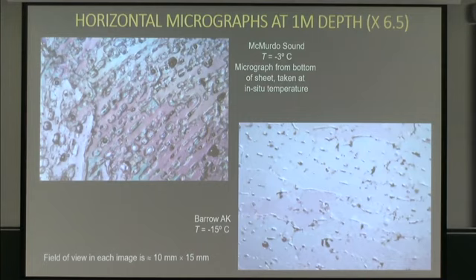So our brine inclusions don't just sit there. It's very dynamic. All these little odd-shaped things you see here are actually tubes and little pockets of brine, but very close, -3 degrees, very close to the melting point. And this was actually photographed at -3, just as a matter of pure luck, down in Antarctica when we were running some experiments one year. But huge volume of liquid brine near the melting point.